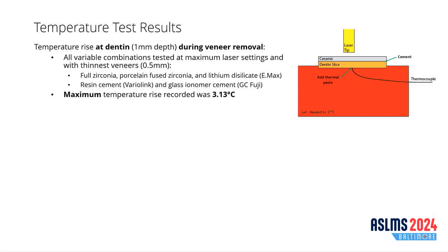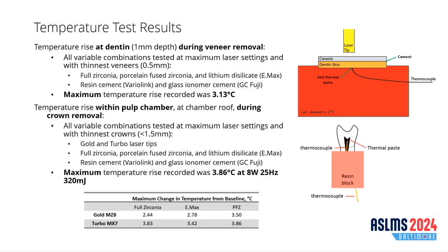Safety was defined as not increasing the temperature more than a few degrees at the dentin or in the pulp chamber. For veneers, they pop off so quickly that we're really just looking at the temperature at the dentin. Maximum increase recorded was 3 degrees. Within the pulp chamber, we filled the pulp chamber with thermal conducting paste and inserted a thermocouple, a very thin wire, up against the roof of the pulp chamber.